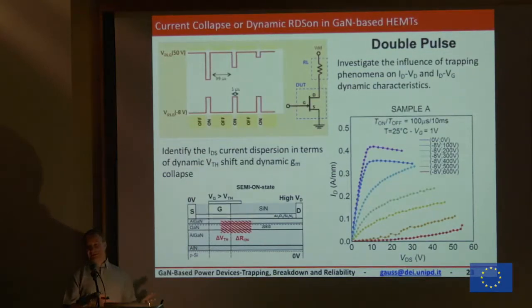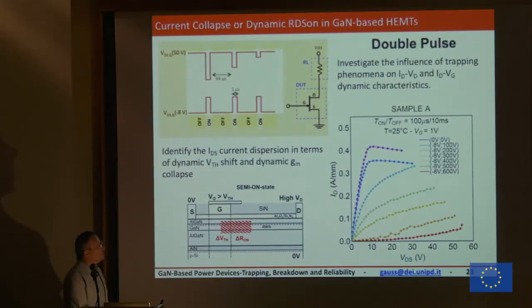We design a device with material properties and with the possibility to have a wonderfully low on resistance, but because of the charge trapping, which does not let the device be completely on immediately, I see a much, much worse RDS-on. So this is what we call dynamic RDS-on. In dynamic condition, my RDS-on is much larger than in a static condition.